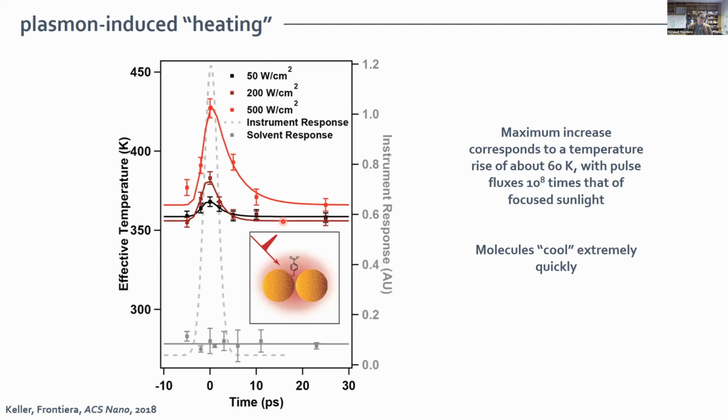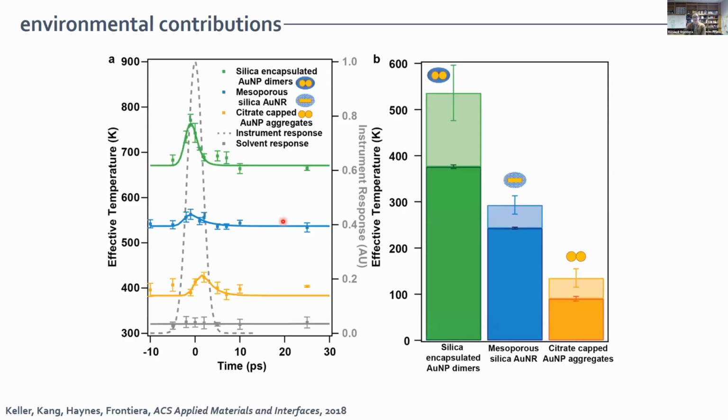So our conclusion from this work was that for many of the applications of plasmonic catalysis, for many of the systems that people use when people are using much lower fluxes, much lower peak powers, these molecules really do not experience very high vibrational kinetic energies, and really heating is not likely a major contributor to plasmon-driven catalysis under most situations.